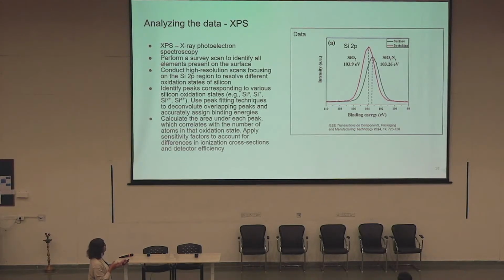They put just the silicon dioxide in XPS and got this particular peak, which is talking about the binding energy of the electron in the 2p orbital of the silicon. Now, when they successfully dope the nitrogen and form this compound, they do the XPS on this sample again, and they're able to see the shift in the binding energy of the electron from the same 2p orbital of the silicon.